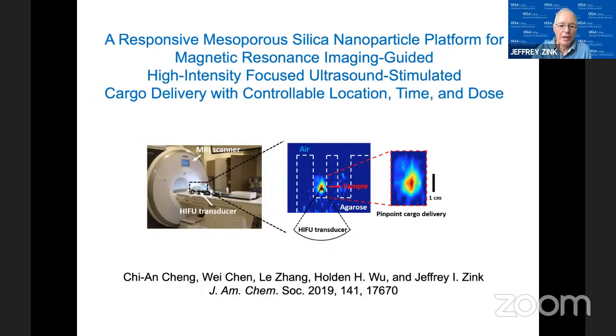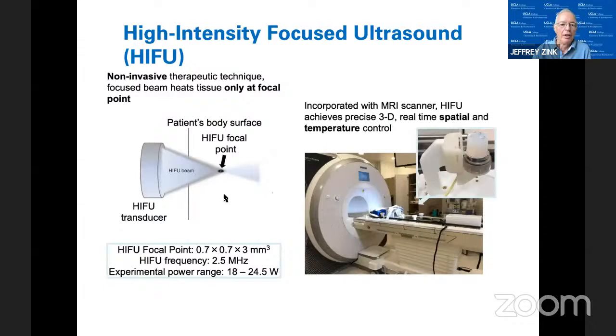Okay, so this is going to be now HIFU external stimulation. The HIFU that we use is shown in the overall left here. The focal point is about 0.7 by 0.7 by 3 cubic millimeters. So it's not as focused as a laser would be, but it's fairly highly focused. Our frequency is 2.5 megahertz and our power range is 18 to 24.5 watts. This is the clinically used HIFU system I'm describing here. And that is just placed under our phantom. And the focal point then is where the HIFU with ultrasound is going to control the nanoparticle. So how do we do that?